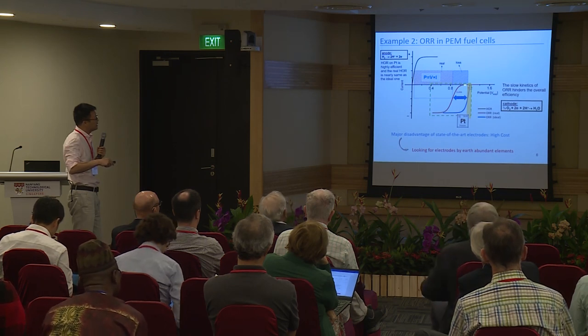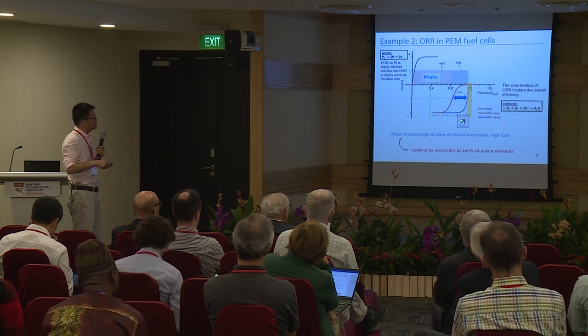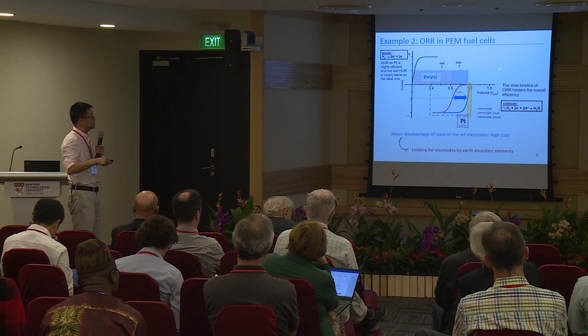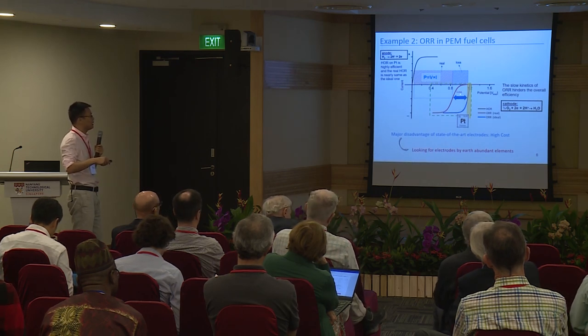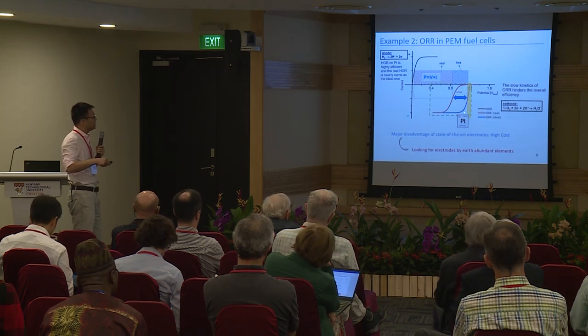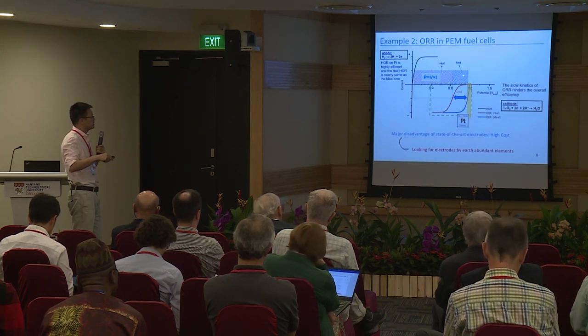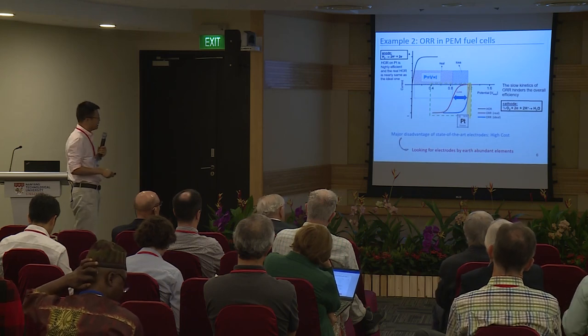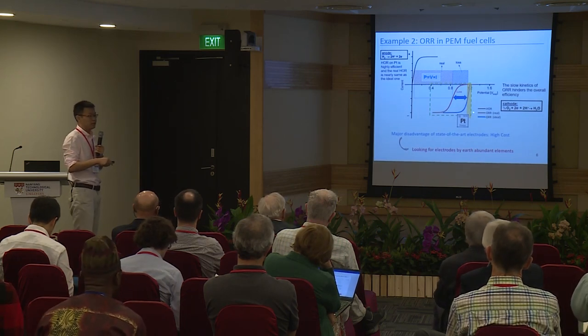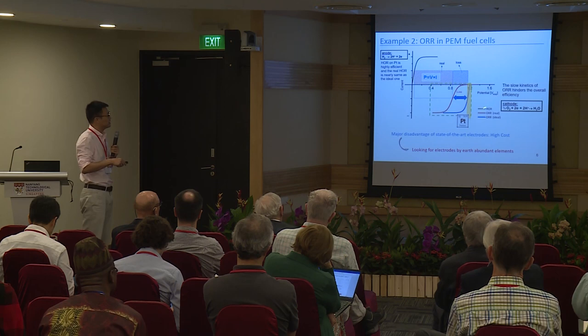This is because at this potential window, platinum surface is oxidized to platinum oxide, and of course your catalyst is blocked by oxides, and the oxygen cannot reach the metallic platinum surface, and there's no ORR happening. Until you apply the potential lower and lower to reduce the platinum oxide back to metallic platinum surface, and then the ORR begins to happen. So this energy loss actually cannot be avoided. So anyway, platinum in the element table is the best catalyst to catalyze the ORR.